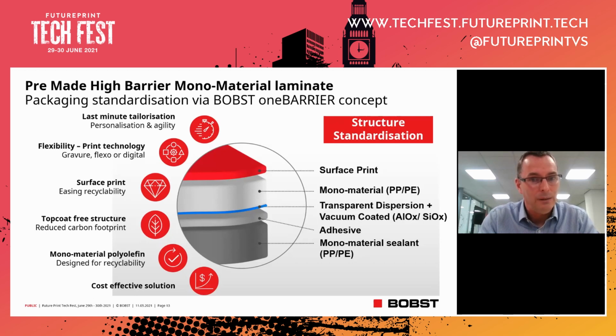Removing the ink layer from the embedded structure also helps to maximize the barrier performance and reduce the barrier loss through the printing onto a brittle or non-protected inorganic ceramic barrier layer.